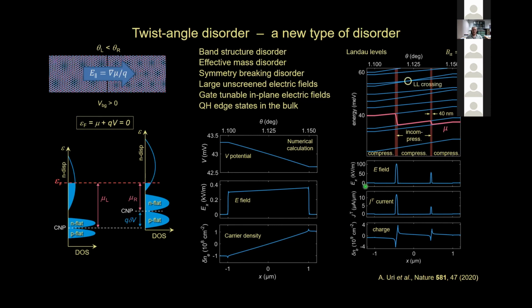And of course also, since the dispersive bands are actually two degenerate bands, slightly shifted in K-space and with slightly different mass, this will result in occasional crossing of the Landau levels. So this is a situation, for example, where we will have 4-fold degenerate Landau levels, followed by an 8-fold degenerate Landau level, and again 4-fold, exactly as we see in the experiment.